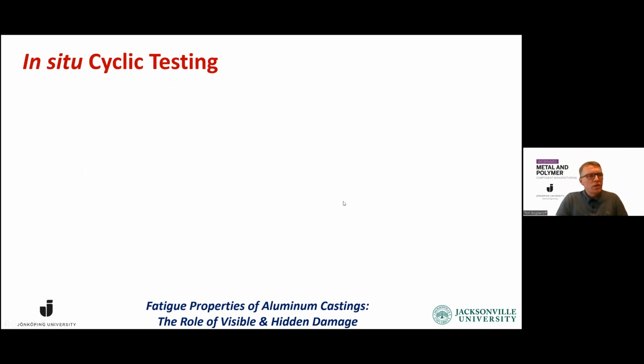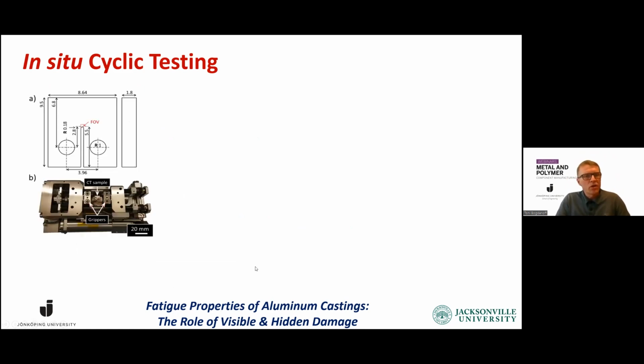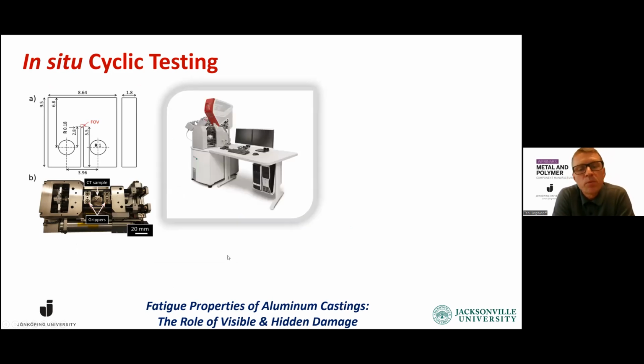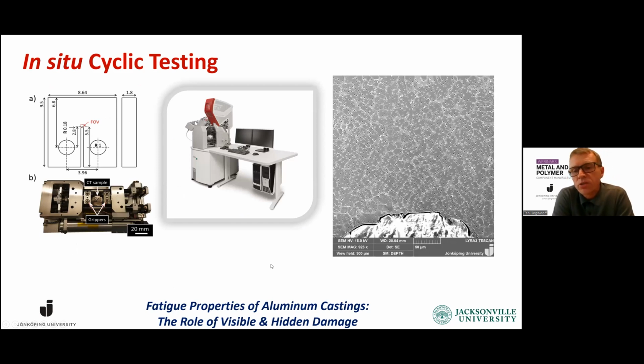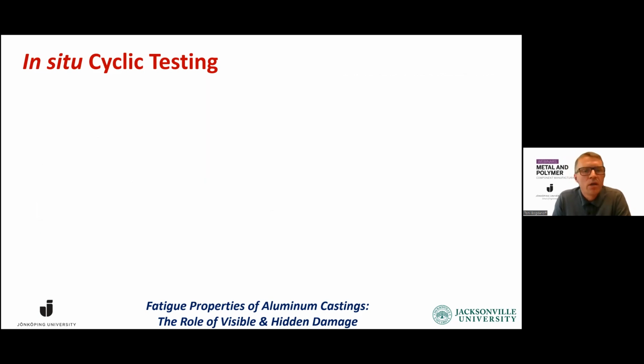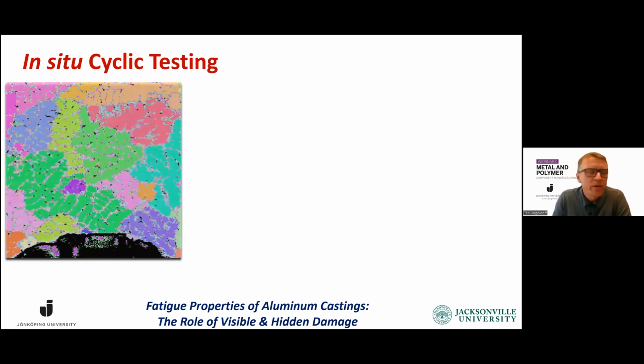What we saw with this one is that I have been using a lot this in situ cyclic testing that we can do here. We have a small stage where we can produce CT samples that we put in our SEM. So we can follow, and this technique gives us a possibility to actually see. This is the field of view that we can see on the A image in this case. So this is what we can see during the start of the fatigue test. What we can add to this is a lot of extra information. We can apply EBSD to get the grain size, so we can actually see if the grain sizes are having any influence at all.